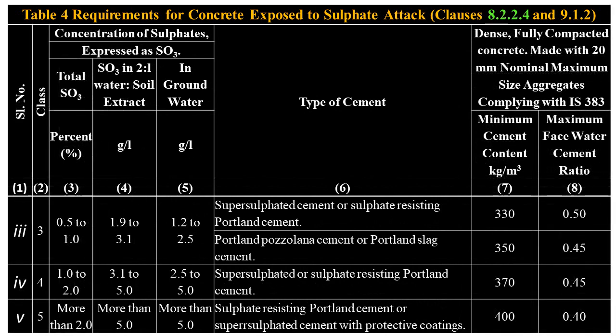In this slide, we will continue discussing Table 4, Requirements for Concrete Exposed to Sulfate Attack, Clauses 8.2.2.4 and 9.1.2. Serial number 3. Class designation, 3. Total SO3, in percentage, 0.5 to 1%. SO3 in ratio of 2:1 water to soil extract, 1.9 to 3.1 grams per liter. SO3 in groundwater, 1.2 to 2.5 grams per liter.